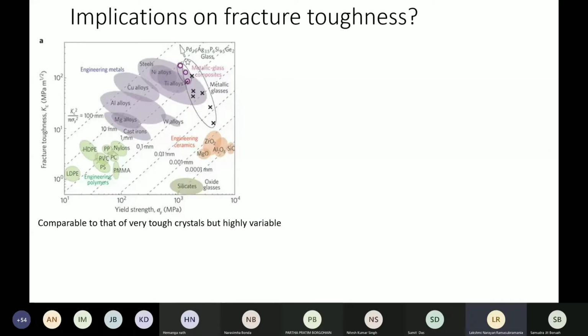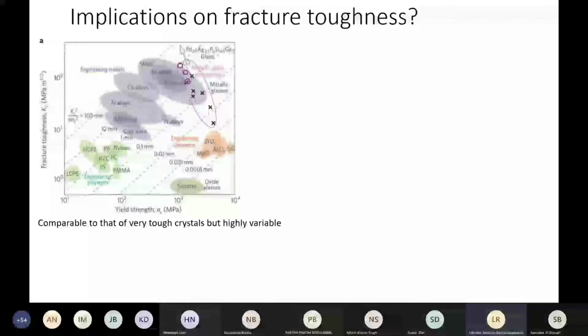So you assume the presence of a flaw, and then you apply loads, and then you see how much resistance a material can offer. And that, of course, depends on the amount of plasticity that develops in front of a crack tip. So going with that, when people measured this fracture toughness, which is measured as K1C, where 1 actually implies that you are applying load in the mode 1 condition, and then when you compare it with the yield strength in this Ashby chart and you put all the materials here, you'll see that metallic glasses are again very high toughness materials.